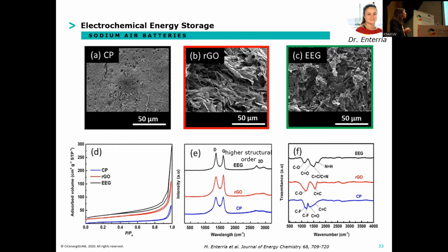So in this one, we also saw that all have a mesoporous nature, but in the case of the EEG, the BET surface area was higher, and also a higher structural order. That was really important to accommodate all this discharge product and to have higher discharge capacity.